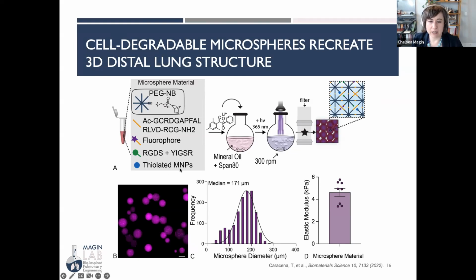We've also included magnetic nanoparticles because part of our process to create the 3D lung structure is to aggregate these together into a cluster to mimic the alveolar tissues. So to make the microspheres, we do an emulsion polymerization. This is just like salad dressing. When you shake up that bottle that has oil and water in it, and you get those little spheres that you can see in the salad dressing, that's what we're doing here. We spin the material quickly. We have an oil phase, and then inside the aqueous or the water phase is all of our material components. This creates small microspheres that we can then polymerize using light. And then at the end, you'll see they look like this.